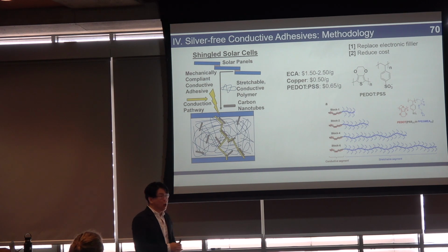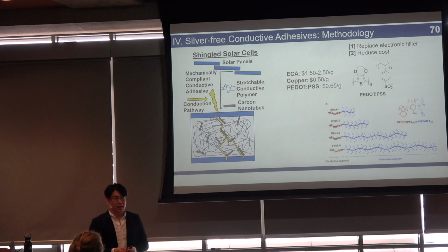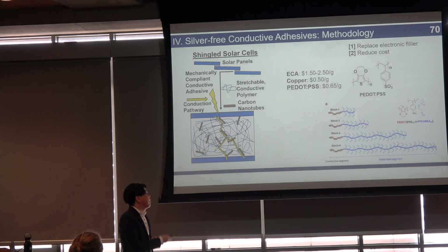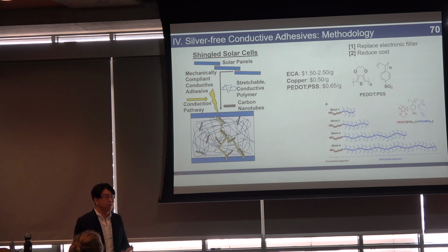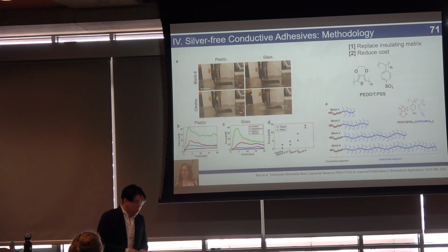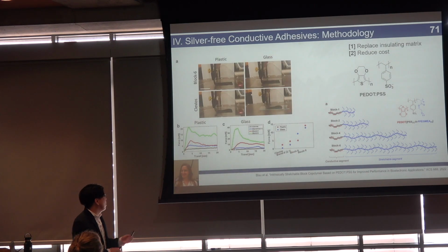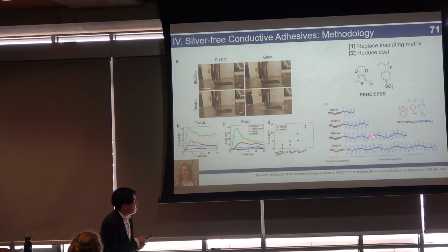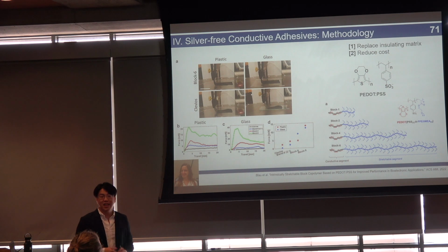PEDOT:PSS is not a scaled polymer right now. It's used in laboratory and research scale applications. And even so, I buy PEDOT:PSS for about 65 cents a gram, which is less than half the price of a conductive adhesive. So immediately we see potential room for improvement, right? This means that we can potentially scale this material for larger use. And previous work by our postdoc, Dr. Rachel Blah, has showed that if you attach this stretchable insulating block, you can also improve the adhesion of your solid film.